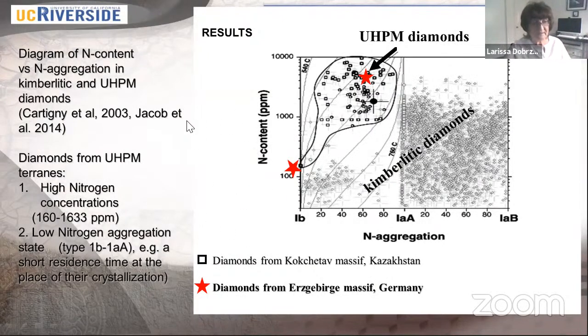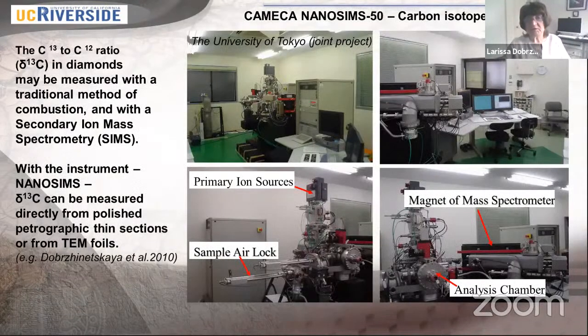So what we see here is that the diamonds from ultra-high pressure terrain have a high nitrogen concentration, in general higher than diamonds from kimberlitic pipes. Also they belong to type 1B, 1AA, but kimberlitic diamond is mostly 1AA, 1AB. So it's a very good discrimination. Then we prefer to work with the same sample, because when you go from one facility to other facilities and you bring different samples, even from the same rock, you can get some conflicting data.